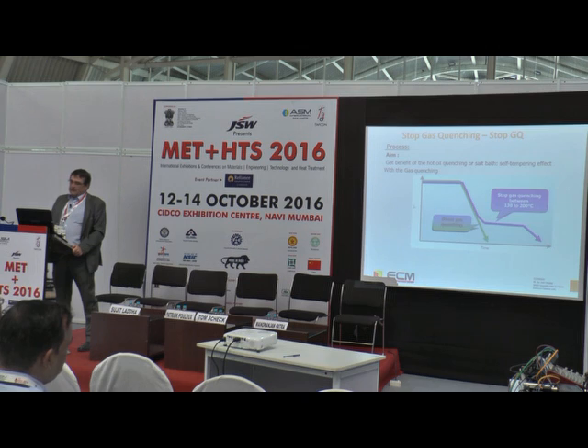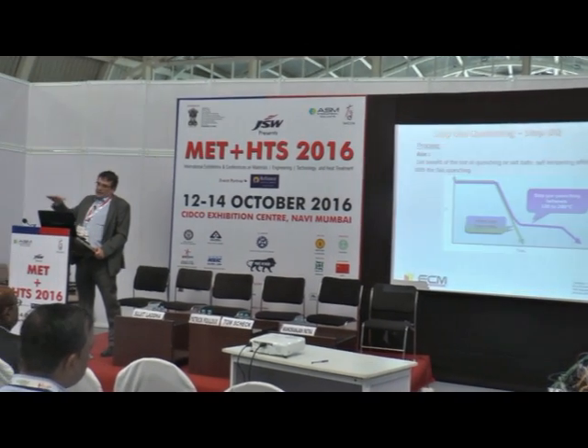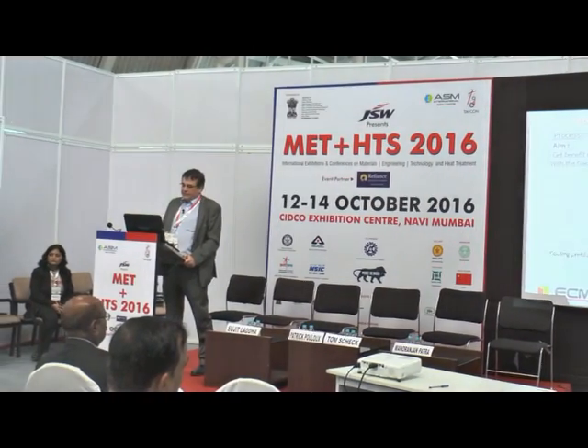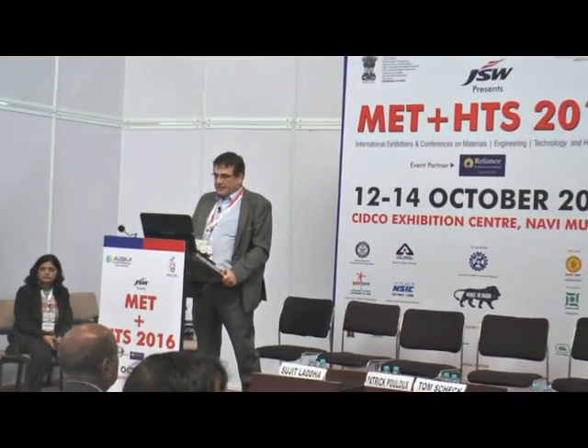Okay. So what happens? The furnace turbine has speed control, and we can adjust it and create a stop quench or self-tempering phases. Thanks to that, we compare 20MnCr5, a case hardening steel, with traditional low pressure carburizing or low pressure carbon nitriding, with direct quenching, or a stop quench at 130, a stop quench at 160, or a stop quench at 240 degrees C, which is represented in this graph.